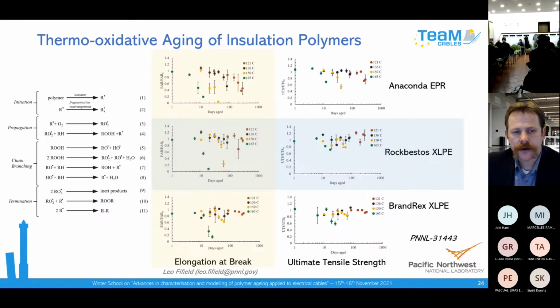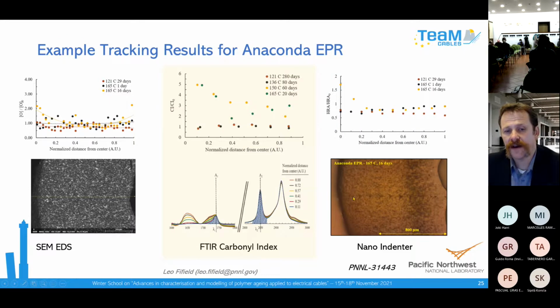So I'll go quickly through these slides. In this effort, we measured tensile properties, elongation at break. You see that the elongation at break values, how far you can stretch the material before it breaks, track with temperature. At the higher temperatures, it takes a shorter amount of time for that elongation at break to fall off. Here's the tensile strength of these materials. So we tried to measure these macroscopic mechanical properties, and then we tried to correlate them with the effect of aging through the thickness